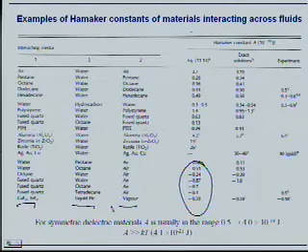Again, if we have, let's say, pentane, water, pentane, two oil droplets in water, they would like to stick together and separate from water. However, if we have liquid helium, solid surface, and vapor, we are going to have quite strong repulsion, which in this case corresponds to the film wanting to get thicker. So how is the film going to get thicker? By sucking liquid helium from the vessel and wrapping itself around the vessel. And as you may immediately guess, this is the reason why liquid helium falls out of vessels.